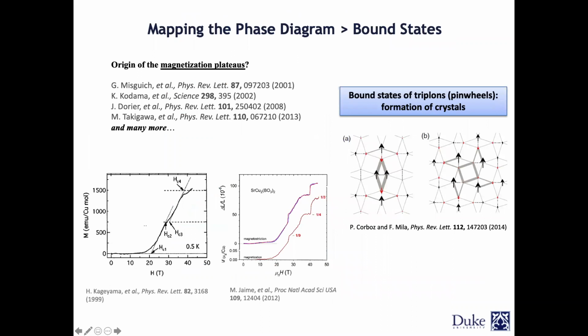Folks started years ago, and many more papers have been published since then, to try to push this to very high magnetic fields and see what this condensation of the triplets into the singlet ground state is going to look like. So initially, they started to see these sort of plateaus. As you can see, this is the magnetization, and this is field. It goes up to 50, for example, Tesla. Nowadays in Japan, actually, they were able to go to 120 Tesla, so it's really high. So anyway, they were able to look at these plateaus, and then they would say, okay, so for example, here, this is 1/8 of the M over M saturation. So let's call this the 1/8 plateau, and so on.